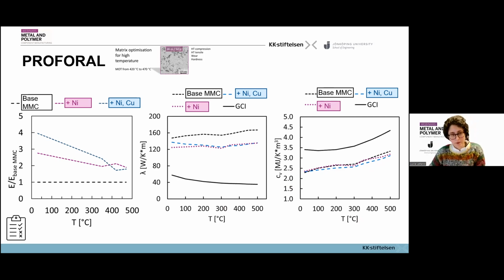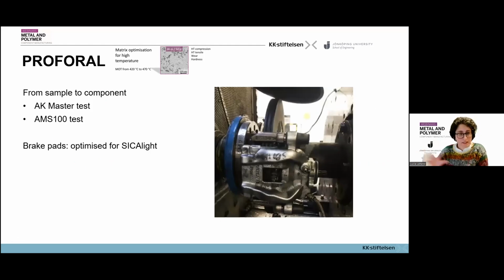So these results are quite promising, and we decided to move on from laboratory scale testing up to now to the component validation. So we produced full-scale brake discs with these two experimental materials, and we went for component testing with the AK master test and AMS 100 test that Samuel just presented, tested against the brake pads that were optimized for the SICAlight material. So brake pads that are optimized for aluminium-based composites. You see here that the brake disc is ready to be tested.